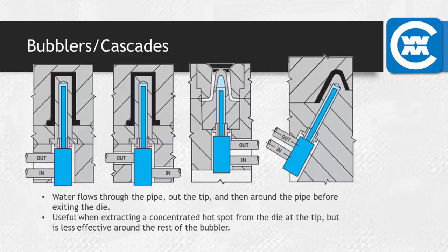The bubbler shown here is a thin-walled hollow tube that is inserted into the cavity. Water flows through the inside of the tube. You'll see it'll come in from here through the tube shown in blue. It'll exit at the tip and cool the tip most effectively. That's where you'll get the highest cooling effectivity. And it'll actually flow down around the outside of this tube and then back out here. So the different examples that you see here are all the same component. They're just installed in slightly different areas on the die.